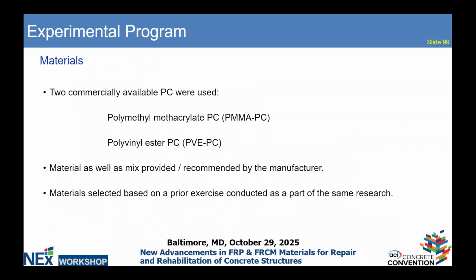For this research, we used two polymer concretes. One is methacrylate polymer concrete, PMMAPC, which is the acronym that I have used throughout, and the other is polyvinyl ester polymer concrete. These PCs were used as recommended by the manufacturer. The resin, the aggregate, as well as the mix were as recommended. There wasn't any mix design performed on our part. We used them as they are. These two polymer concretes were selected based on a prior research where we did a comprehensive comparative study of 6 different types of polymer concrete, and we found these two to be among the better ones. So we went with these two for this part of the research.